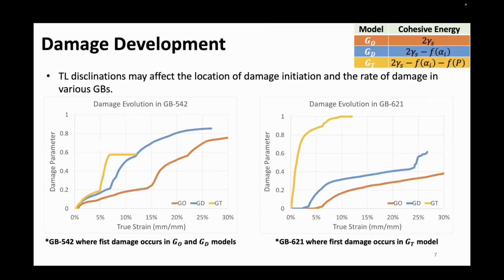And here are two plots to support our discoveries. This plot shows the damage progression at different grain boundaries. As I mentioned, the damage initiated at different grain boundaries. For the GO and GD models, they start at the same grain boundary, which is GB-542, and for the GT model that involves the triple line, it starts at GB-621. Not only do they start at different grain boundaries, they also propagate at different rates. In this figure, all three models start at a similar strain, and the GT model quickly accumulates and reaches a value of 0.6 around 10% strain.